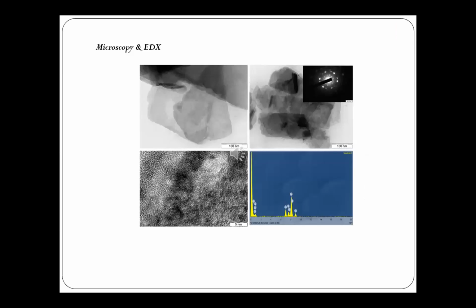Yeah, so here we can see, this particular material was further examined for its morphological aspects and composition. Here we can see the EDX pattern, which shows the presence of nickel, cobalt, oxygen and so on, which confirms the formation of nickel cobalt hydroxides. Also, the TEM images depict the layered accumulation of hydroxides of nickel and cobalt. So we can see the layers of accumulations of hydroxides, which again pronounces the formation of nickel cobalt double hydroxides. Further, the microstructure was examined using HRTEM, high resolution TEM, and SAED patterns.